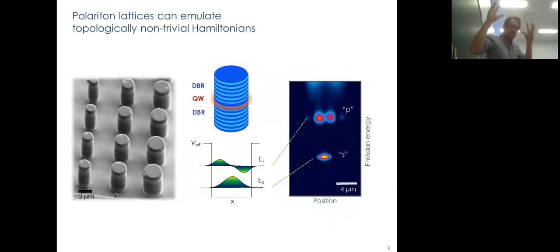And so, as I said, we can use this as our backbone, and we can etch these cavities to form artificial materials. We usually rely on an approach based on the tight binding approximation. The building block, so each atom, is described by these micropillars. These are several tens of microns in height, several microns in diameter. We obtain them by etching the planar cavity that I was showing earlier. As a result, photons are confined vertically by the Bragg mirrors and laterally by the variation of index of refraction. So we have photons that are confined in all three dimensions.